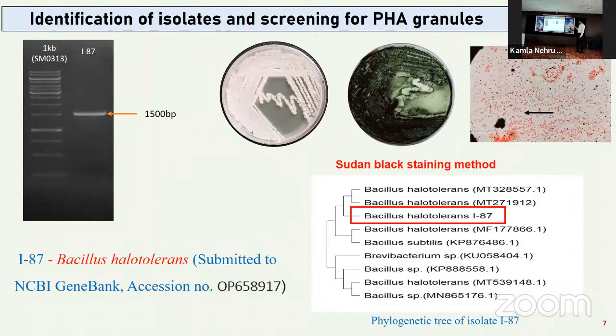So this is a slide. It was identified as a Bacillus halotolerant species, a non-pathogenic commensal organism. We checked for its halotolerance. It grows well up to 10% NaCl, but it's not really a halophile. It is a halotolerant species, and it grew best at normal physiological NaCl concentration. So it was fit for our purpose, and it was identified by 16S rRNA sequencing. Its PHA production we analyzed by Sudan Black staining in plate as well as under the microscope. It showed PHA granules.